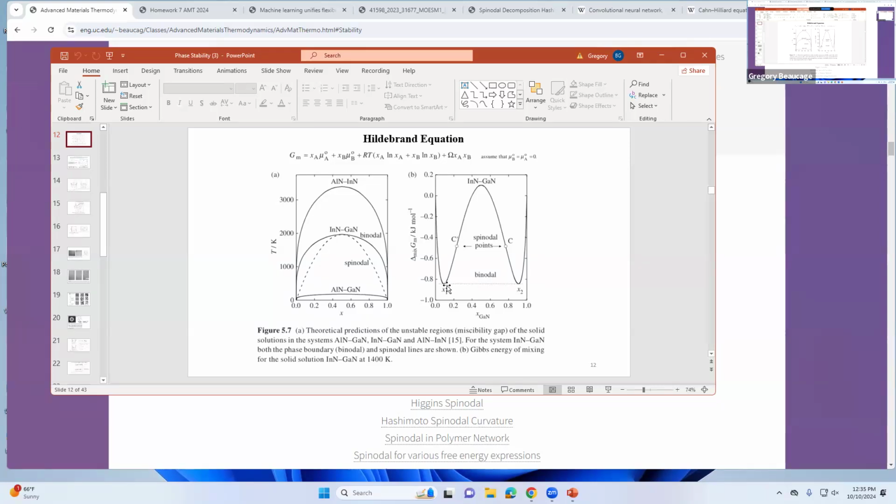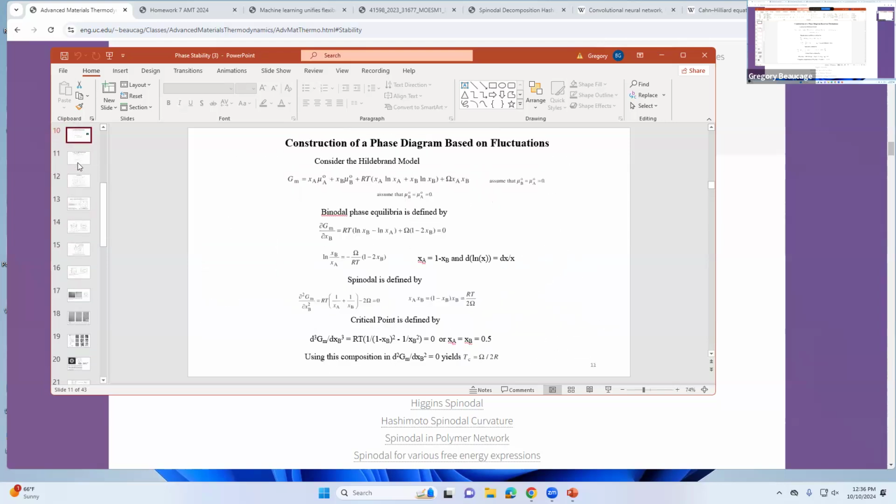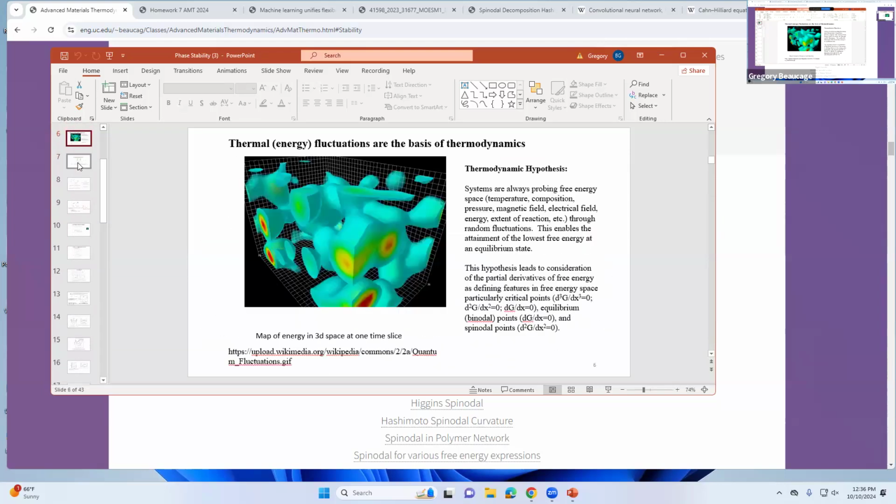But the equilibrium points are here. So if you're in this region, you need a nucleus to phase separate. It has to grow on dust or something. If you're in this region, it spontaneously phase separates because this frown thing wants to dump the phases. In the spinodal, it just decorates the fluctuations that already existed in the system. Like in this picture, it says there are composition fluctuations. So it's just going to grow on top of those.